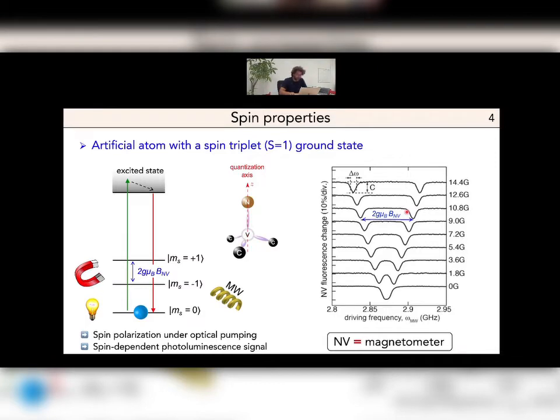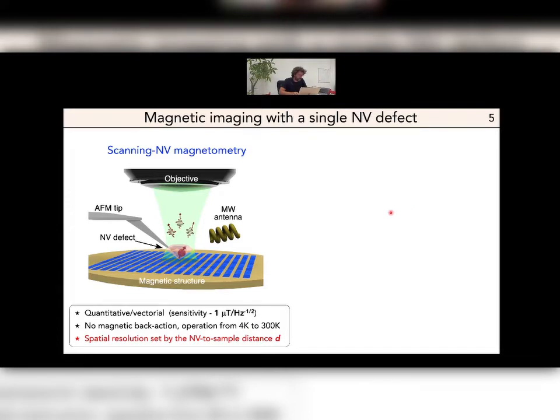If you now want to make a magnetic microscope, as I mentioned before, you need to integrate it in a scanning probe unit, and this is the principle of a scanning NV magnetometer, where you have a single NV defect that is grafted at the apex of an AFM tip. On top of the tip, you have a microscope objective that is used both to excite the NV defect with a green laser and also to collect the spin-dependent photoluminescence. You have a microwave antenna, which is used to perform electron spin resonance on the NV defect. And the idea of the experiment is then very simple. You just bring a magnetic structure that you scan, and at each point of the scan, you record the Zeeman shift of the electron spin resonance, from which you extract the magnetic field distribution.